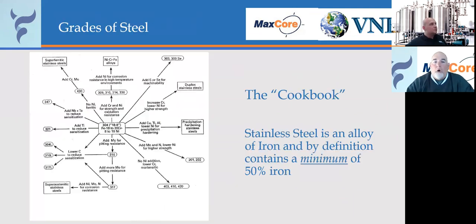So if you look at the cookbook, when you're talking about making steels, here's what we start off with. In the middle, we start off with an 18-8 stainless steel, just a straight grade 304 stainless steel. By adding these different alloying elements, you come up with different types of materials. By adding more molybdenum, 2 to 3% molybdenum content, you get a 316 stainless steel. You can reduce the carbon and get into your low carbon grade steels. You can add more molybdenum and add nickel and nitrogen, and you get into your super austenitic stainless steels. So depending on what alloying elements you add to the base metals, you create a different melt of steel.